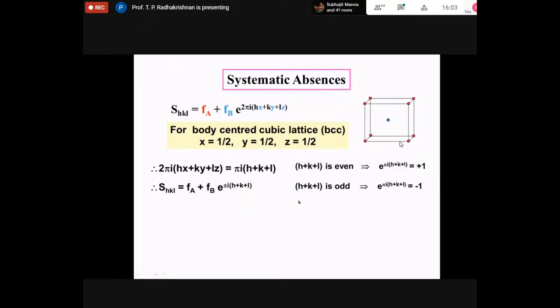Why? Because if H plus K plus L is even, then e to the power of an even multiple of pi i will be 1. It will be cos 2 pi plus i sine 2 pi, for example, which is 1. But if this number is odd, for example, cos 3 pi plus i sine 3 pi will be minus 1. You can verify this from trigonometry. So whenever this summation is odd, this exponential will be minus 1. When it is even, it will be plus 1.